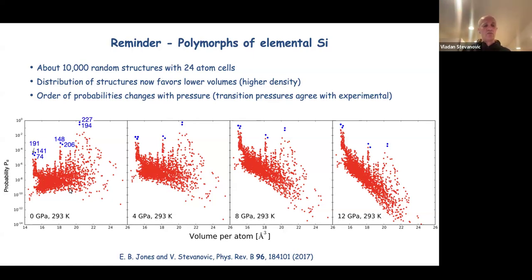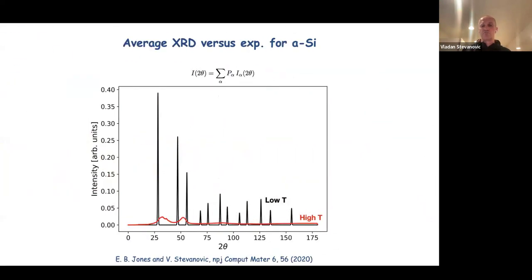And in order to investigate that a little bit further, the two quantities that we averaged first were just the long range order and short range order quantities. The first one was just the X-ray diffraction, so the modeled powder X-ray diffraction. And because we are doing ensemble averaging, we can do that at low temperature and at high temperature.